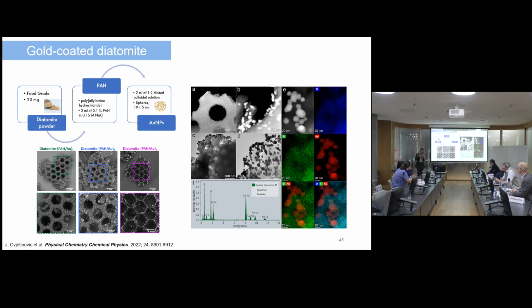So they tend to find the optimal place along these edges, along the pores. And then after each deposition cycle, they tend to accumulate beside those so-called favorable places, upon deposition of polyelectrolyte and nanoparticles. So if they accumulated along the edges during one deposition cycle, upon the next cycle they will tend to accumulate along these nanoparticles that were along the edges.